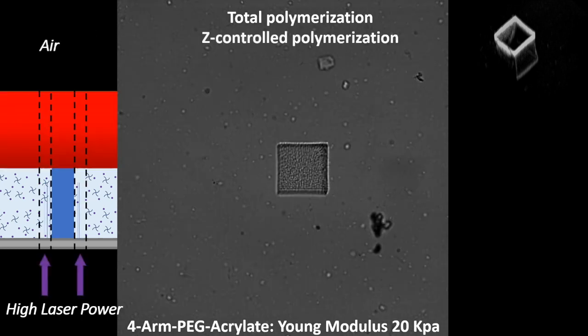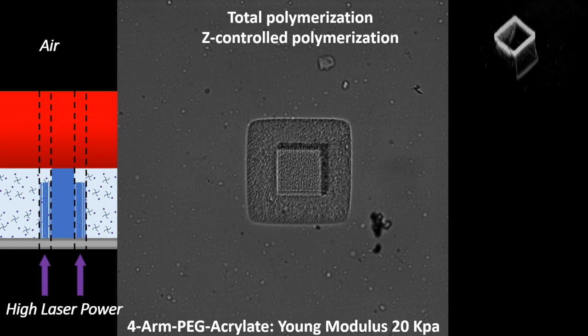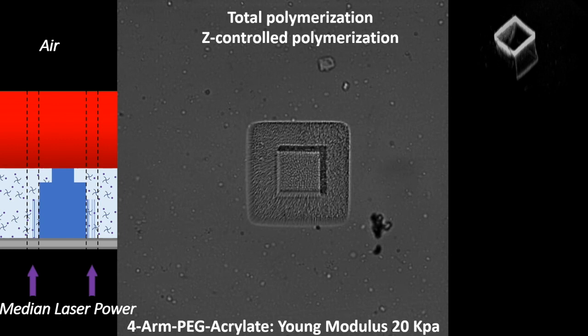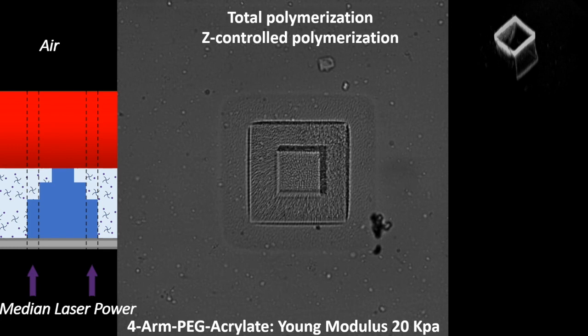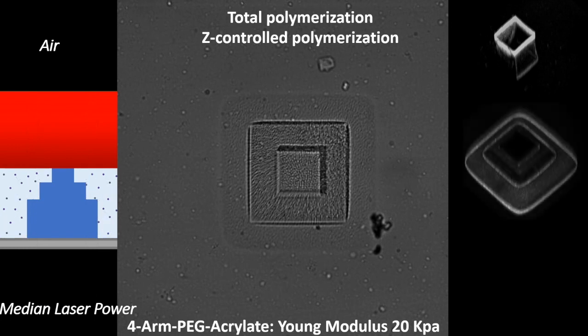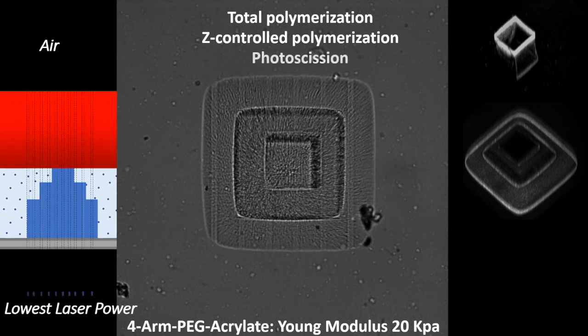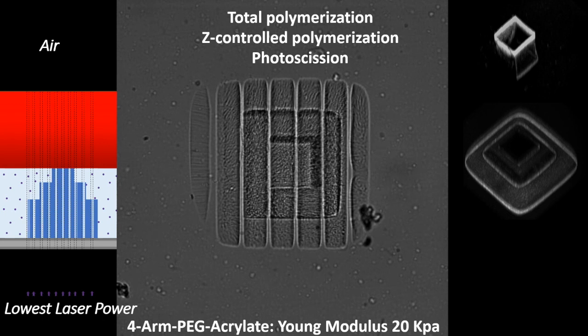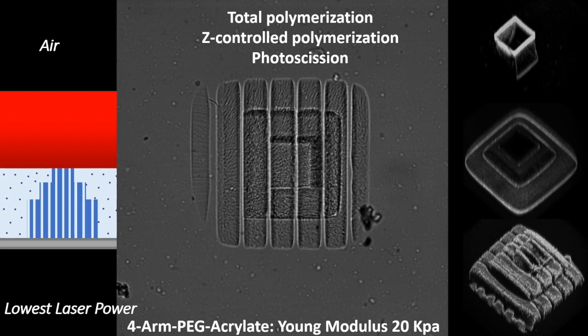In a second engineering process, we control the polymerization thickness by adjusting the photon flux. This Z-controlled polymerization exploits the inhibition effect of oxygen contained in the air. Last but not least, we also use oxygen for a subtractive structuration method. During photocleavage, we liquefy the hydrogel in the illuminated volume. Overall, oxygen gives us three structuration methods, which are complementary with our decoration method that I will describe now.